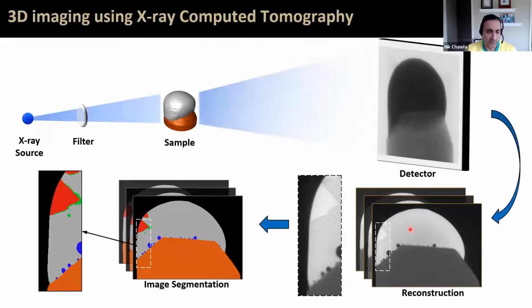So some examples might be, in this particular microstructure, the size of bismuth particles, the porosity that develops during the solidification process. In a mechanical testing kind of experiment, you may need to quantify crack density, tortuosity of the cracks. One of my students, Guilherme, is actually doing tortuosity of dendrite branches in a magnesium alloy. So things like that can be used in a very innovative way to understand the physics of the problem and exactly what's going on in that fourth dimension.